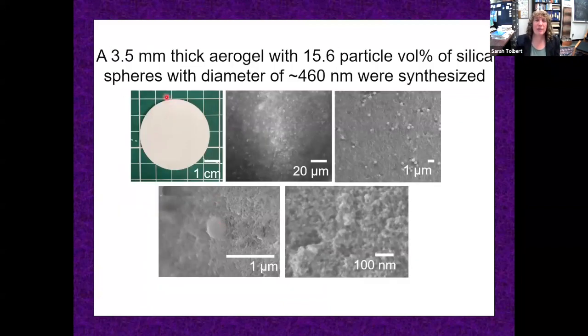So here's our material. They look white. That means they're scattering light. On a big length scale, 20 microns, they look homogeneous. As you zoom in, you can start to see those big scattering colloids. As we zoom in more, we can see one colloid embedded in a porous network. And then as we zoom in more, we can see this whole porous network of silica. So this is our daytime radiative cooling material.